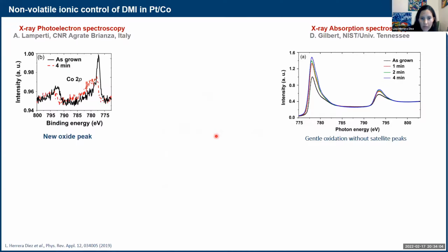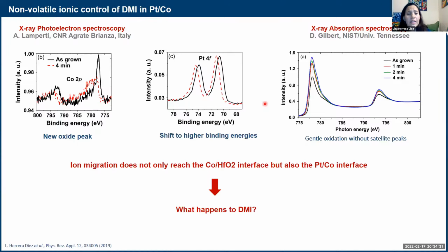So to confirm this, we did some experiments with our collaborators in the US and in Italy. We did what I showed you before already, this X-ray photoelectron spectroscopy. We could really see the signature of an oxidation of the metallic cobalt. And we could also see the signature in X-ray absorption spectroscopy. So it's a change in the amplitude of the main peak. But what was interesting as well is that we could see a change in the platinum edge. We could see a shift in these peaks. So this was an indication that the chemical environment of the platinum could be affected by the ions.